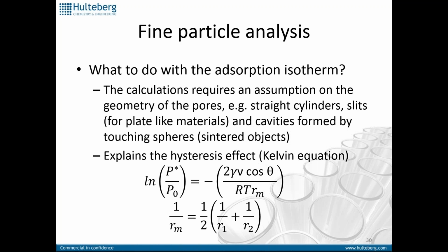And I normally use the desorption isotherm because to me the pore mouth restriction is the one that we need to consider when it's about diffusion and stuff like that. But other people may have other opinions on that. So you should get your own opinion on this topic.